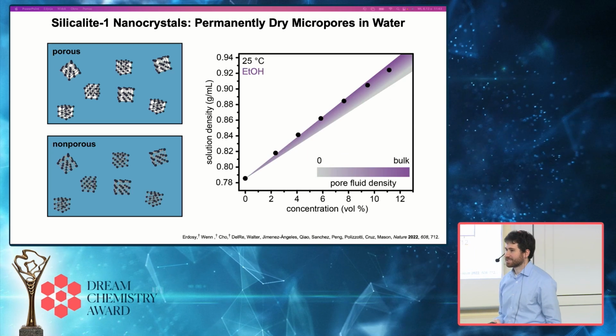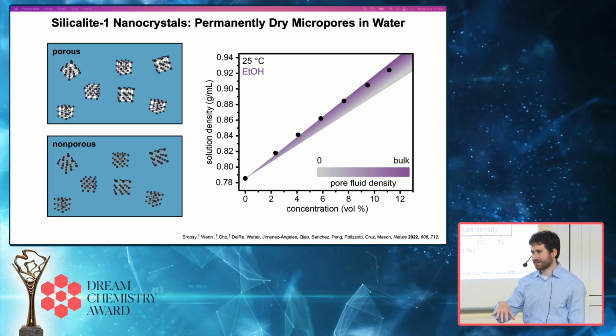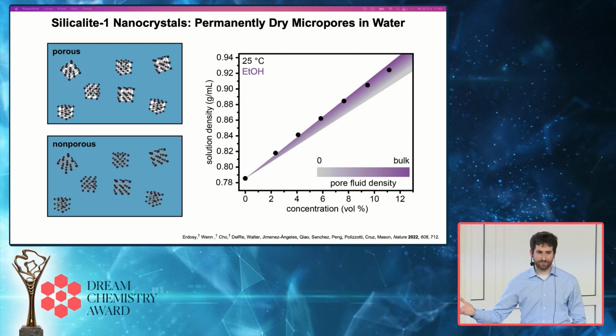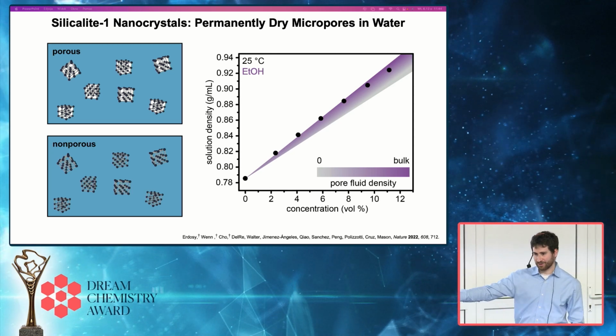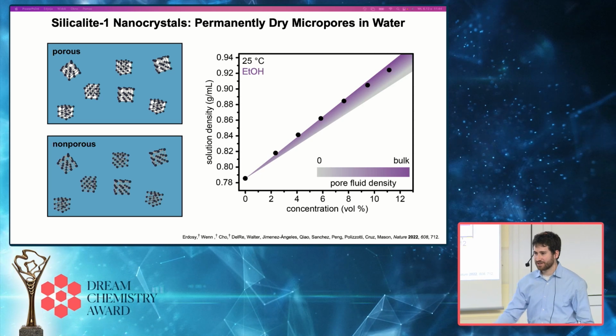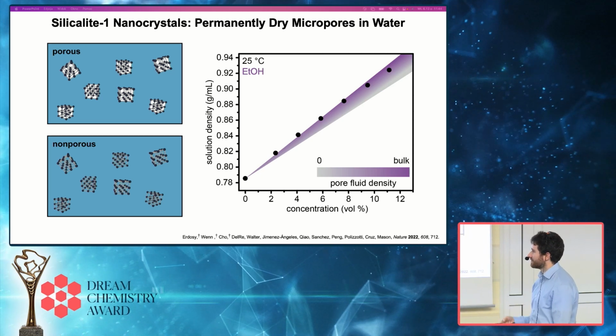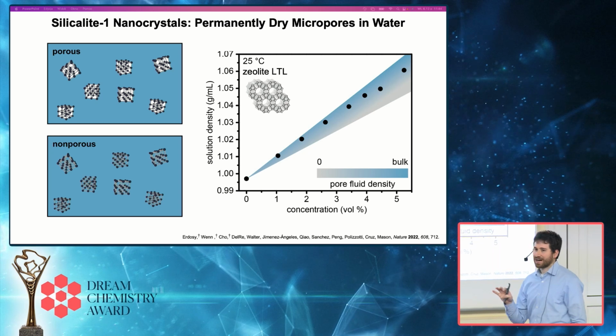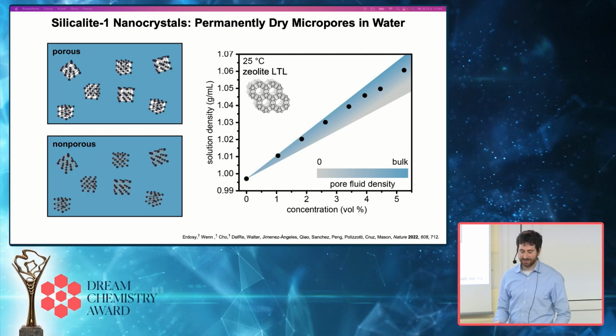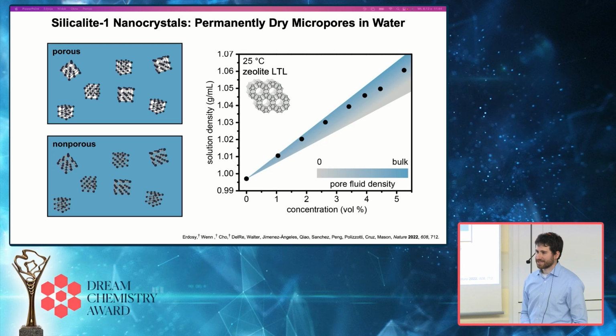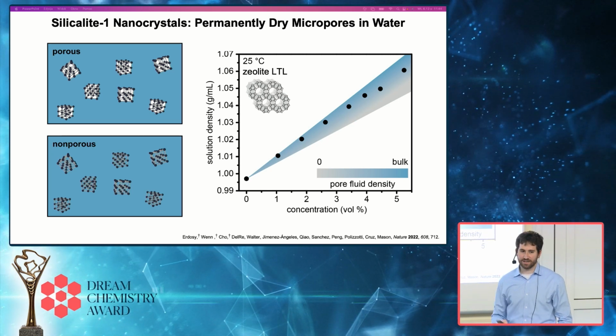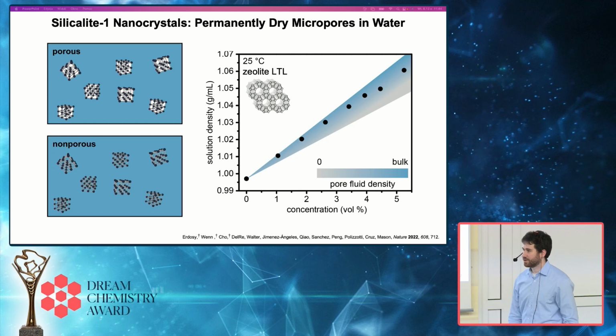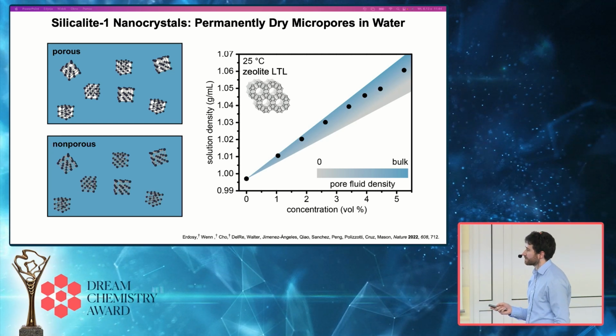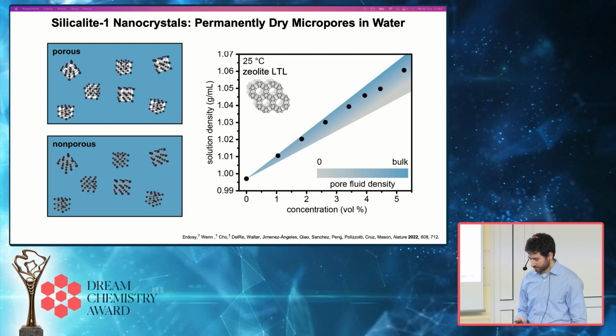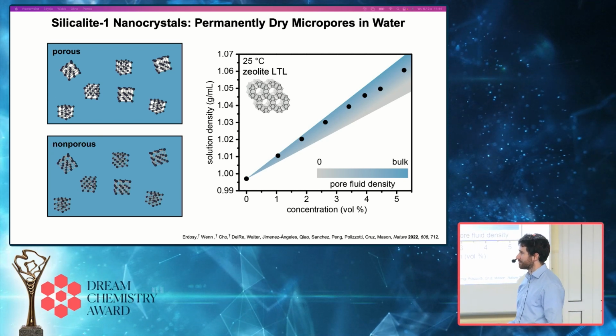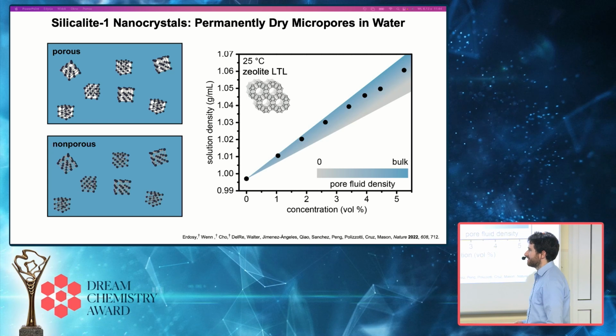And this was in contrast to what we see if we use a less polar solvent like ethanol instead of water. We would not expect it to be thermodynamically unfavorable for an alcohol to go in the pores. We would expect that to be thermodynamically downhill. And we see densities that are consistent with having solvent-filled pores. If we use a hydrophilic zeolite instead of a hydrophobic zeolite, so this is just another zeolite that contains a mix of aluminum and silicon cations, and its pores are charged, and so they're quite hydrophilic, then we see densities in water that are consistent with having water inside the pores. So this convinced us that the pores were likely dry inside these colloidal dispersions.